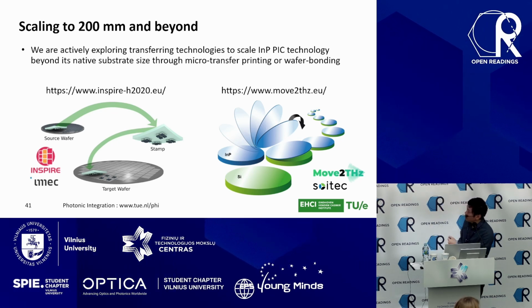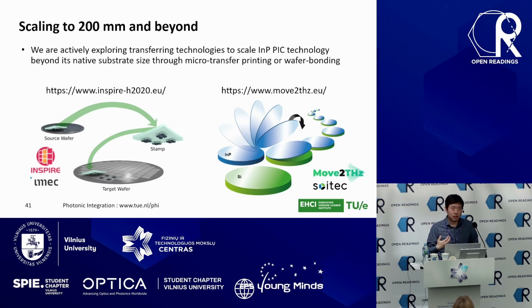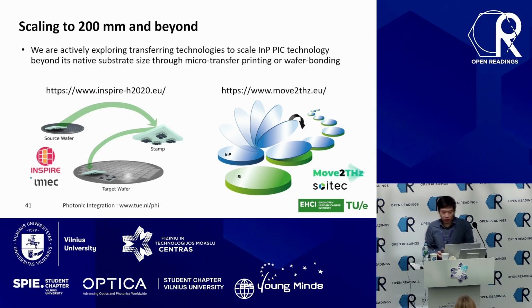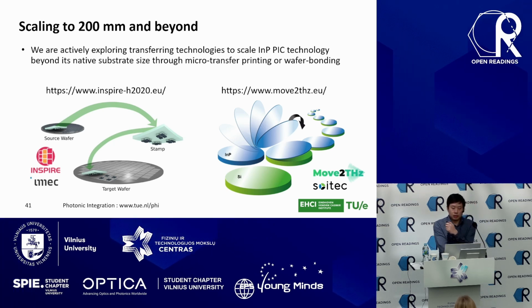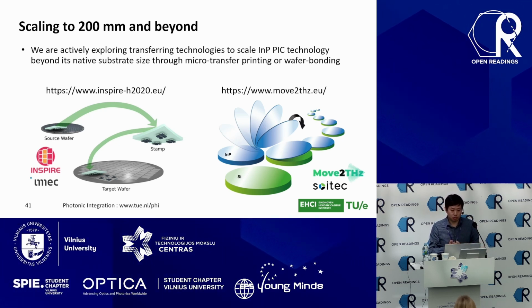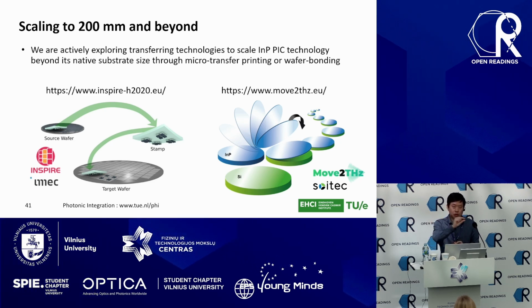And also in another program, we are trying something even more radical. If you know how an SOI wafer is made, it's basically bonding of 2 silicon wafers, right? And removing the substrate of one. This was invented by this company, Soitec. But the same principle can be applied to indium phosphide on silicon as well. Why not bond indium phosphide to silicon wafers and then use what they call smart cut technology to remove the indium phosphide substrate? Then you have an indium phosphide seed layer, right on top of your silicon surface.